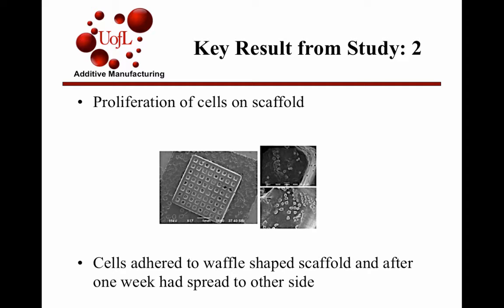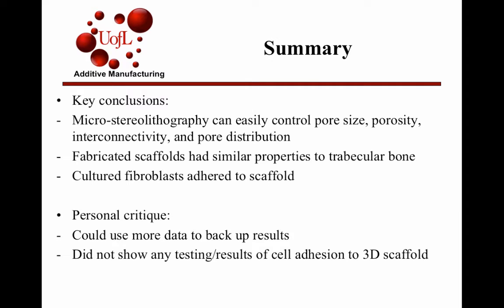And in conclusion, microstereolithography can easily control pore size, porosity, interconnectivity, and pore distribution. The fabricated scaffolds had similar properties to trabecular bone, and the cultured fibroblasts adhered to the scaffold.